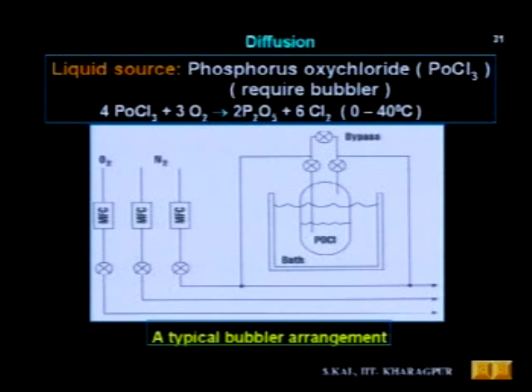Okay. Now, normally for POCl3 diffusion, we keep the temperature of the POCl3 container at 0 degree in our case. That arrangement is there in our laboratory, you can see it. And before diffusion starts, we pour the bath with ice, lot of ice, so the temperature will be 0 degree, will maintain. The reason is that at 0 degree the POCl3 will have certain vapor pressure.